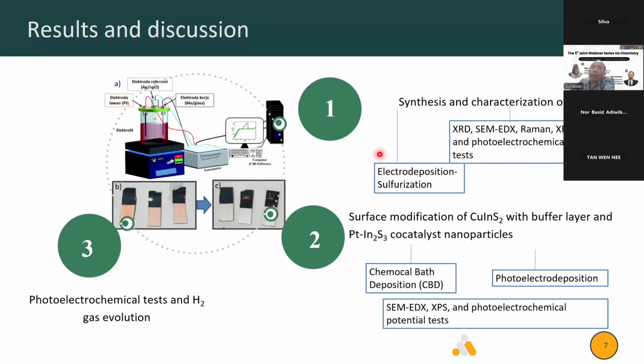After characterization, we do surface modification here. And then we also do SEM, EDX, XPS, and photoelectrochemical tests. And then for the photoelectrochemical test and H2 gas evolution, we do it in the third step here.